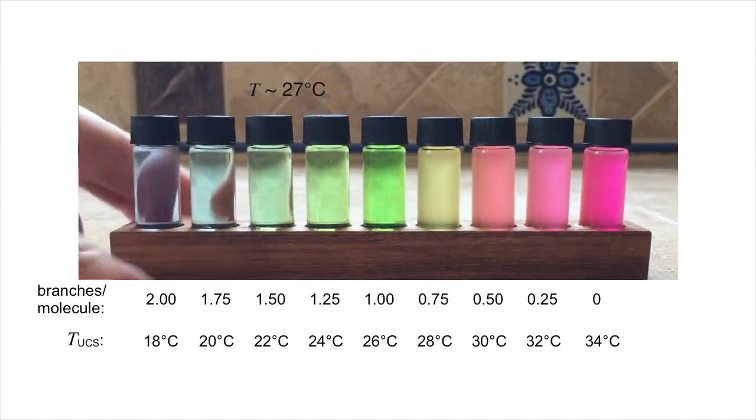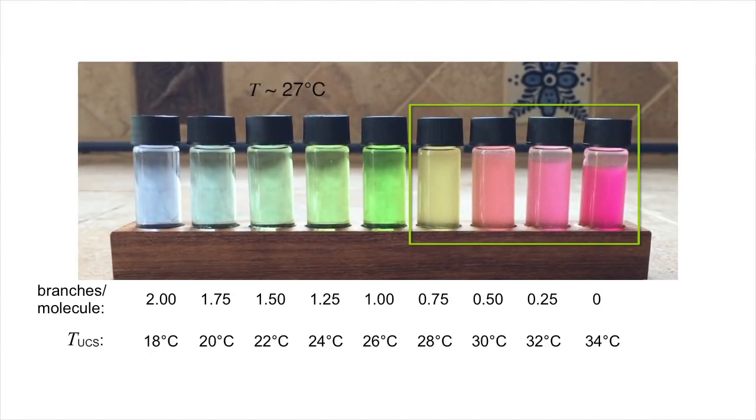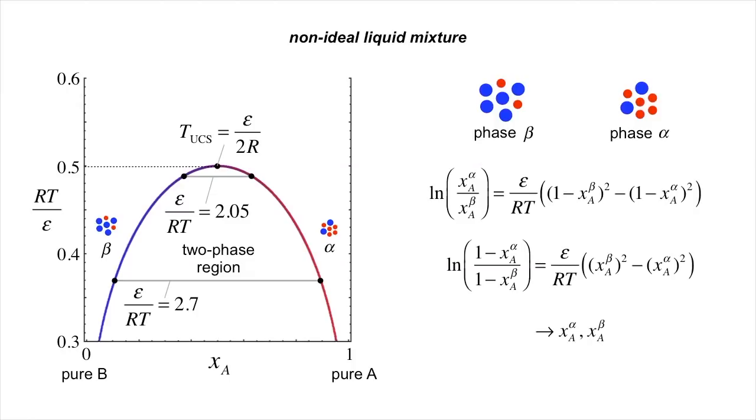As an aside, we can also see that the rate at which phase separation occurs is slowest for solutions closest to the upper critical solution temperature. This suggests that the density of the 2 phases become more similar near the critical solution temperature. This is consistent with our scaled phase diagram, which shows that the composition of the 2 phases approach each other near the upper critical solution temperature.